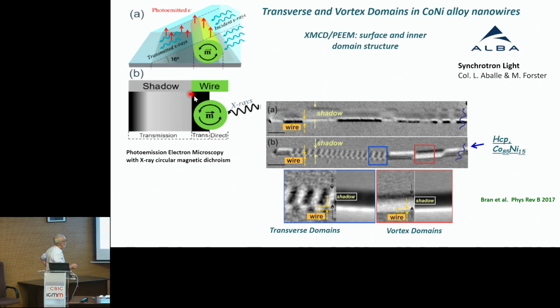For example, this is an example for this HCP hexagonal nanowire. You see this is a completely different magnetic domain structure in different regions of the nanowire. Here we have a multi-domain structure, multi-domain transverse domains. Well, here these different contrasts are interpreted as two magnetic vortices with different chirality. So in one, the magnetic moments are rotating in one direction, and in the other, in the opposite direction.